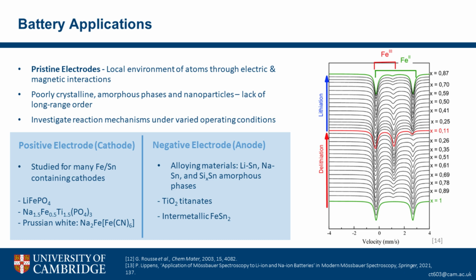These are just some examples of how it's been applied to battery materials before. I'll highlight alloying materials here, as they might be particularly interesting. And then here, just to show an example of lithium iron phosphate, where by looking at the Mossbauer superimposed with the charge cycling, they were able to quantify the exact fraction of iron 2 to 3+, and map it to the charging position of the battery.